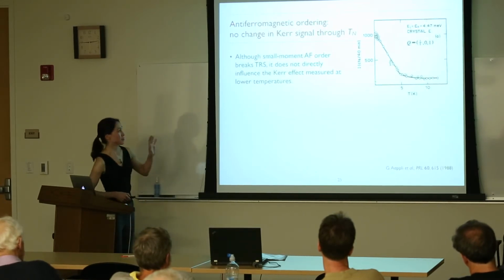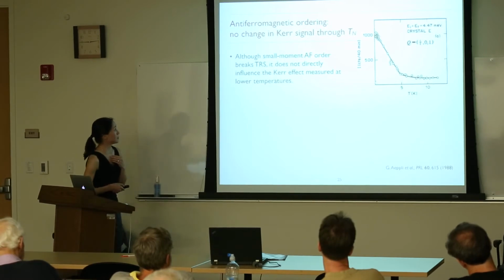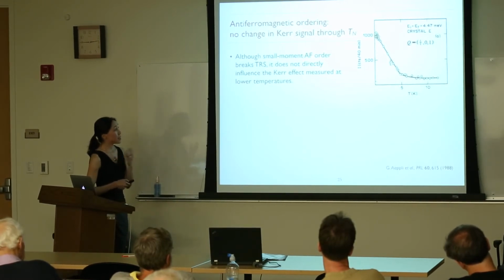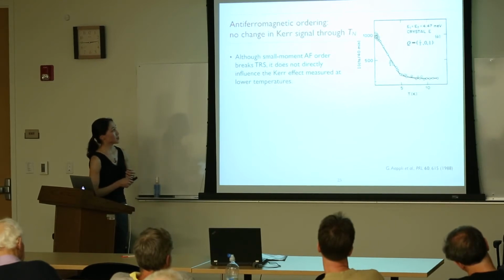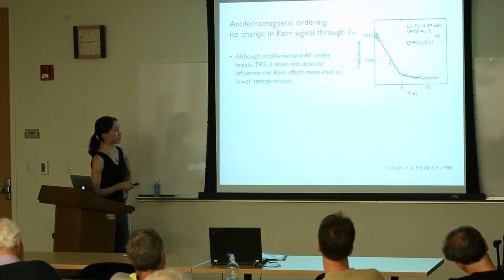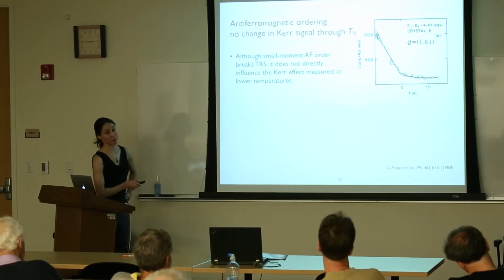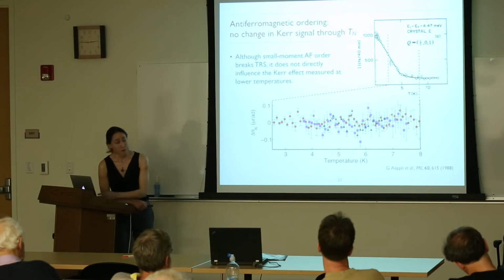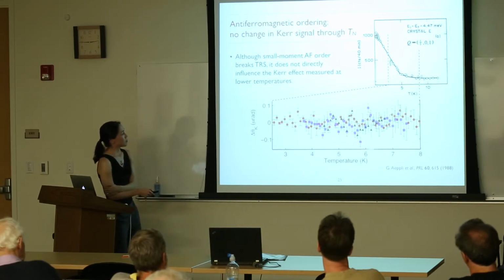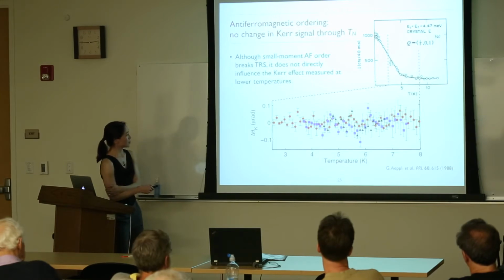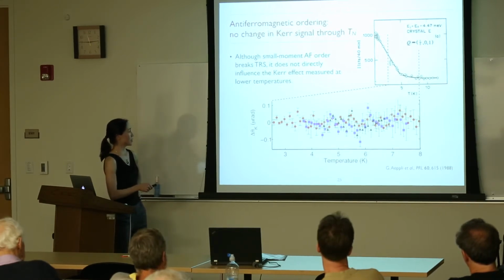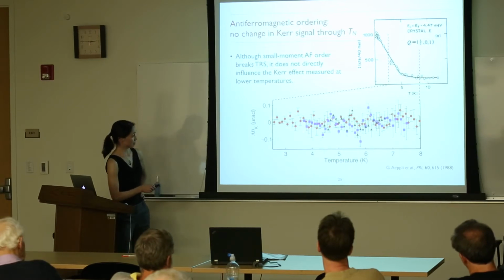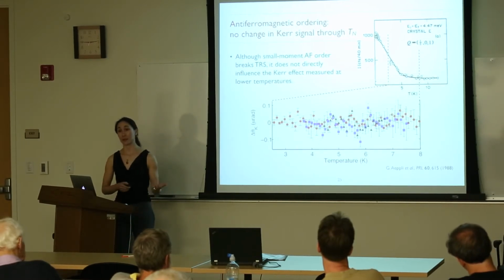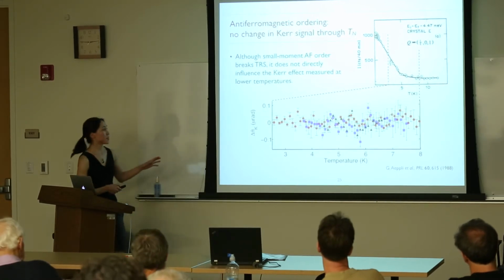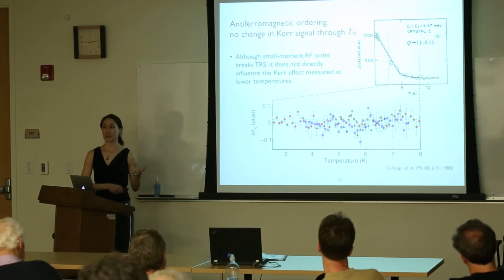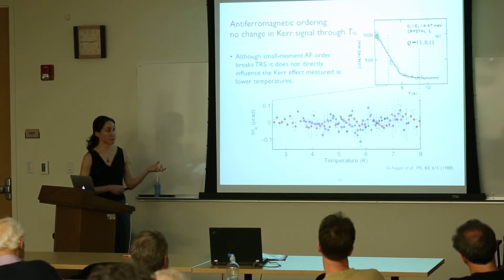Okay, so moving through our list, the first thing again is to think about antiferromagnetism. As I said before, there may be a small antiferromagnetic moment. So this was some neutron scattering data showing the onset of this order at about 5 Kelvin. And what we see if we look at Kerr effect, this is just a blow up here, is really not a whole lot. So 100 nanoradians is about the size of this here. And the different colors are basically just different field cooling conditions. But the point is that as far as we can tell, there's nothing going on in terms of Kerr effect as you go through the antiferromagnetic transition.